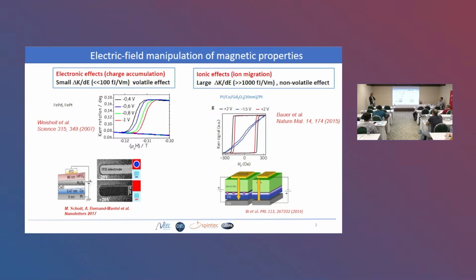So all this until very recently, this voltage manipulation with electric field was associated to electronic properties, so accumulation or depletion of electric charge at the Fermi level, and this gives rise to quite small variations of the perpendicular magnetic anisotropy, just a few percent.